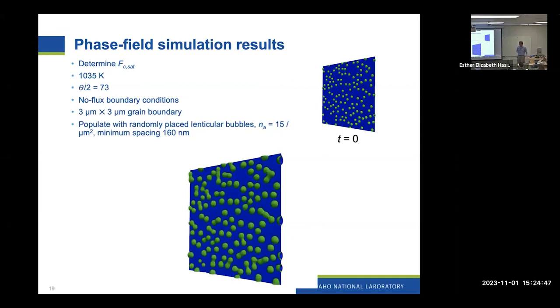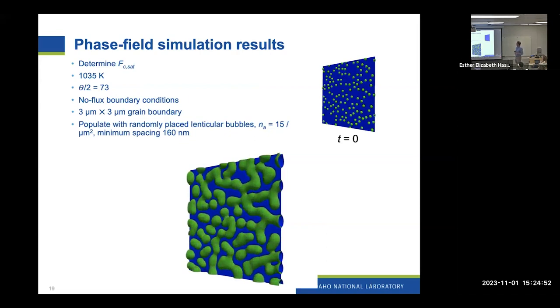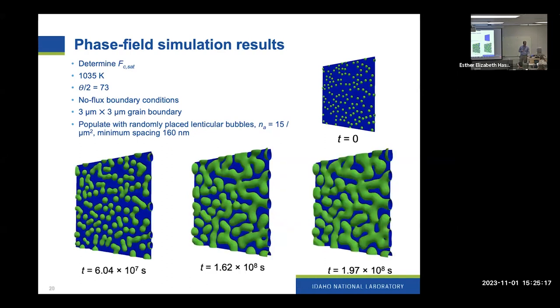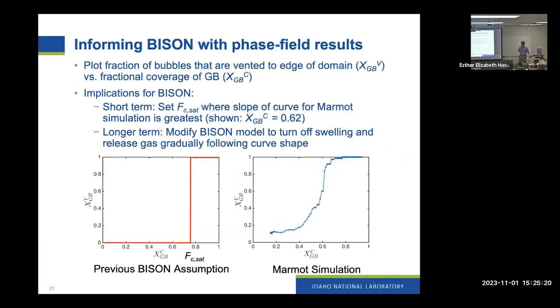Hopefully this movie will, okay, it actually plays pretty well over Zoom, which is nice. So we set up our initial conditions with representative temperature. We set the dihedral angle based on the atomistic calculations. I think the size of the grain boundary is representative of what you'd see in U3Si2 fuel, and we set the initial number density, as I said, based on those rate theory calculations. Okay, this was just my backup in case those movies didn't play, but I think you saw that reasonably well.